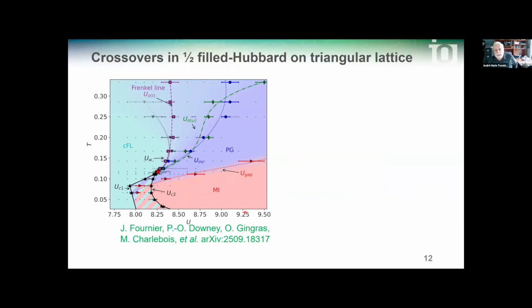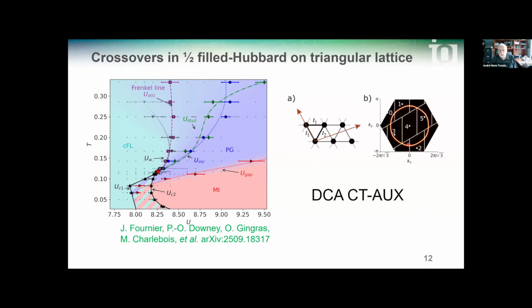Let me start with crossovers in the half-filled Hubbard model on a triangular lattice. This is a model that may apply to layered organic superconductors. The advantage is that long wavelength fluctuations associated to ordered ground states are estimated to happen at temperatures lower than the Mott transition. So we can focus on the physics of the crossover associated to the Mott transition. The method is DCA on a 6-site cluster with a CT-AUX solver. I assume that everyone who follows this series of seminars is familiar with this type of approach.